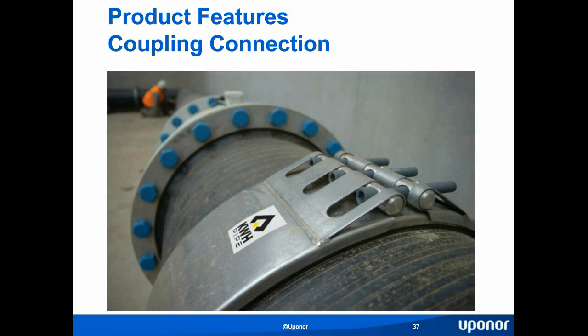We also can offer a band coupling. This particular band coupling is not only pressure rated, but it is leak free. The advantage to the coupling is that if you are in a trench where there's considerable water and you can't dispose of the water, say you're on a side street doing a sanitary sewer project and you have no place to put any groundwater you're coming across due to environmental regulations, you can use this band. The reason you would want to use the band is because you can't weld in wet conditions. So this is why we offer this band. It is quick, reliable, contractor friendly, and it gets the job done as well as the welded joint.